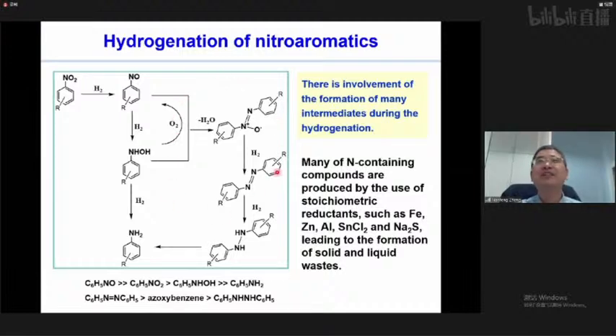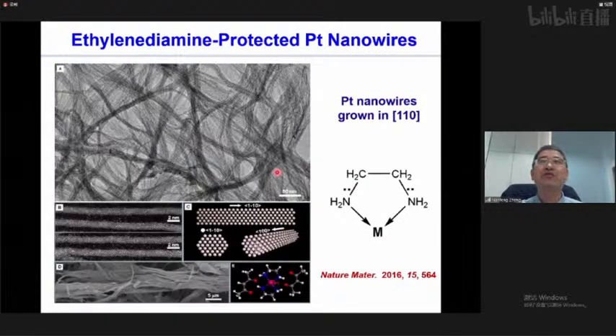Okay, so several years ago, we tried to use palladium platinum nanowires as the model catalyst. And I would like to mention here that all these nanowires, their surfaces are only covered by ethylenediamine. Initially we considered this shape so important. But after years of study, we realized that the shape is not important at all. It's because of the bonding of ethylenediamine on their surface.